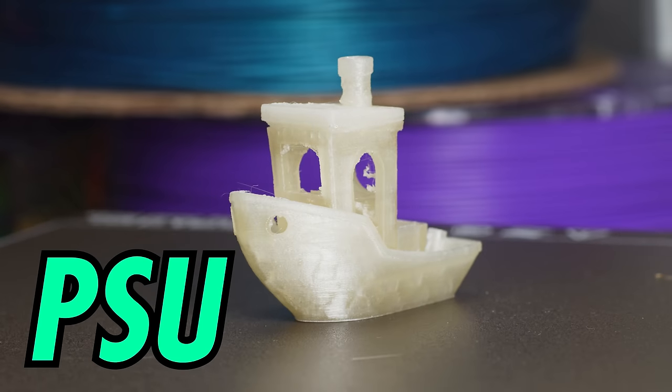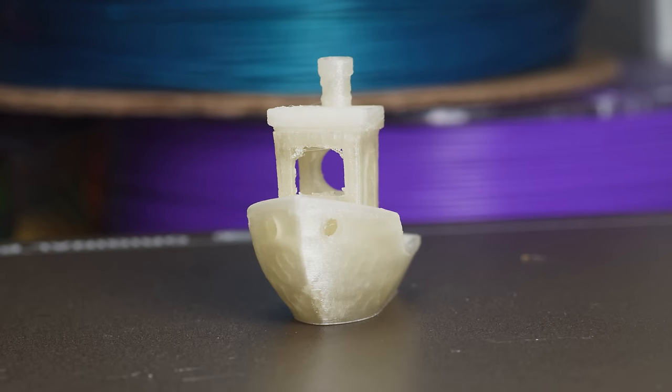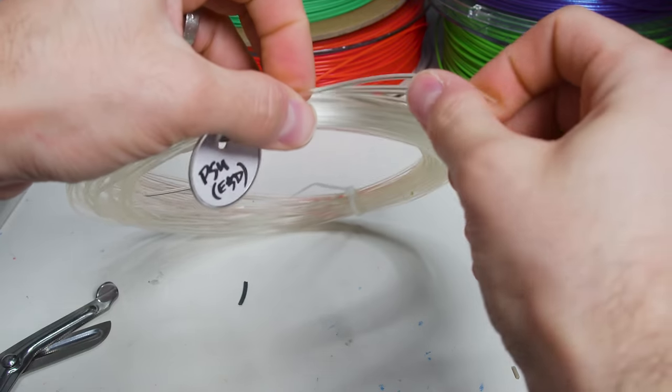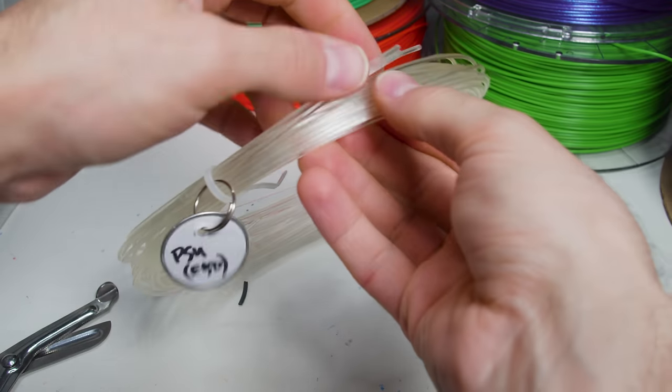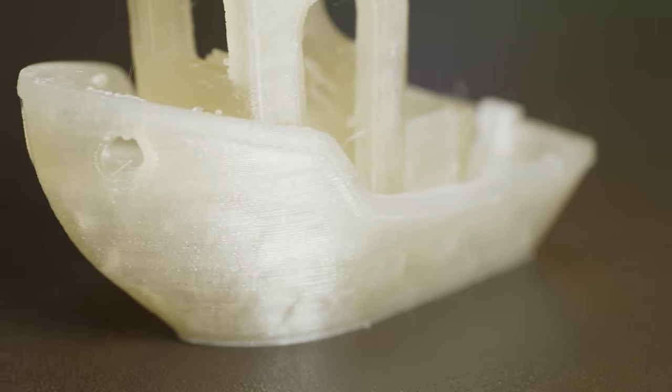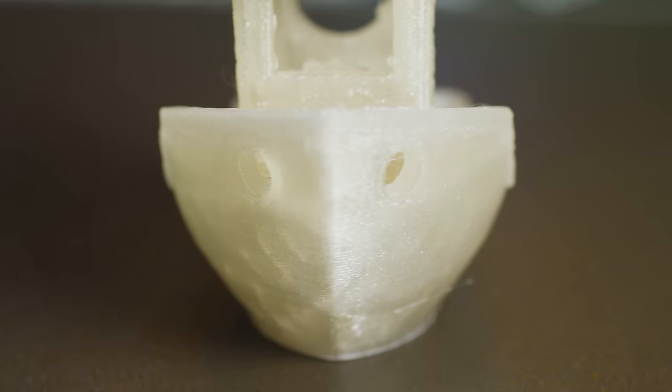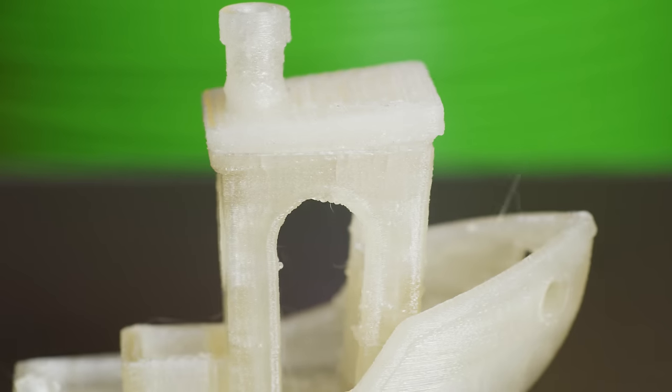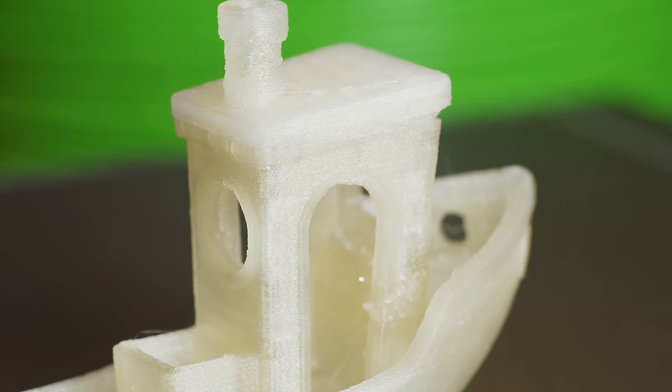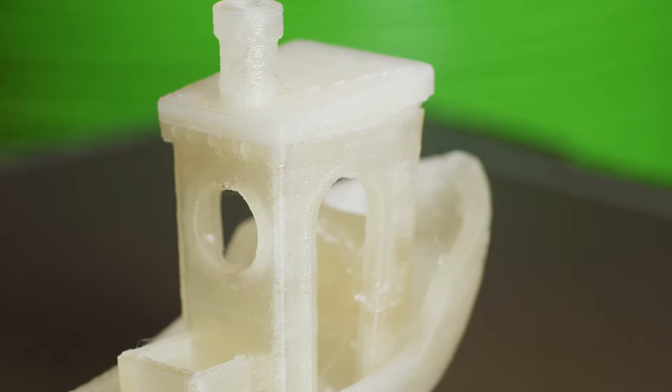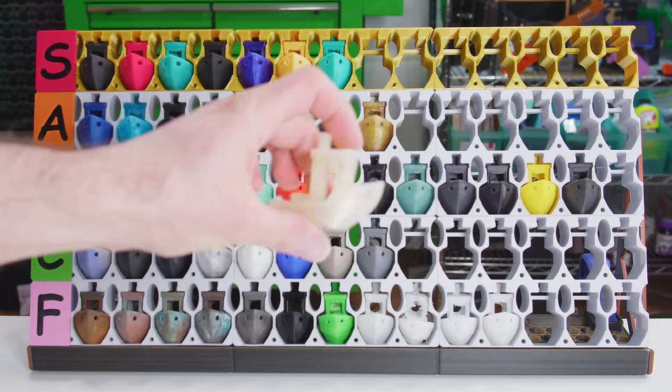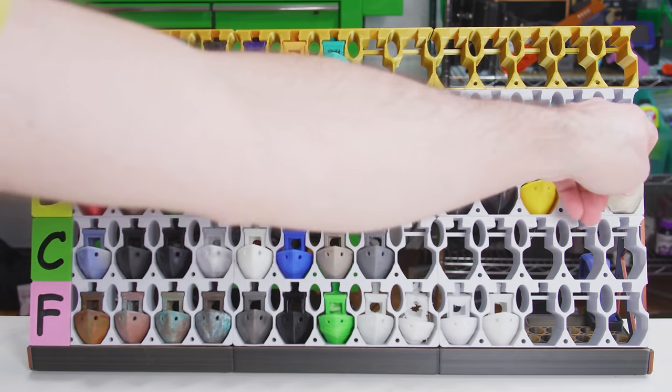PSU. Polysulfone, not power supply unit, is the weakest superpolymer, with mechanical properties about the same as PA6 nylon. But PSU's glass transition temperature is an astronomical 187 degrees Celsius, and it keeps its strength almost the whole way there. You can literally print a nozzle out of PSU and use it to print PLA. It also shrugs off water, radiation, and chemicals. And when you combine that with the heat resistance, you can sterilize PSU as if it were surgical steel. I'm gonna put PSU high in the B-tier. Nylon is almost always gonna be a better choice, but PSU opens all kinds of new frontiers in citizen science.